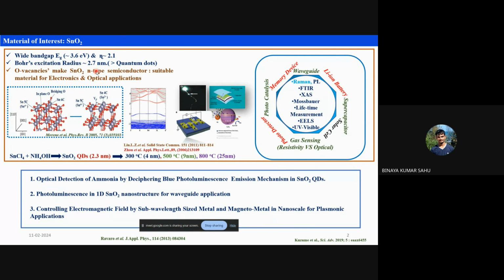Like we have seen in quantum mechanics and classical mechanics, there are two different designs. Quantum mechanics is very interesting because of its special effect on the material property. A material will start showing quantum properties when its size comes down to the Bohr excitation radius, and that is different for different materials. For tin oxide, the size is around 2.7 nanometer. So by any means, if you are able to make tin oxide below 2.7 nanometer, it will start showing very different properties as compared to the bulk, and that can be exploited for various applications.